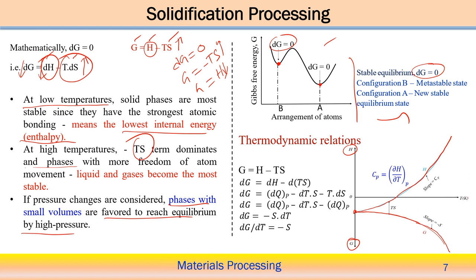If you see, as the temperature is increasing, the Gibbs free energy decreases. That means a more negative value. So Gibbs free energy decreases with increasing temperature. It means that if we make a boundary here, the higher temperature side represents the existence of liquid and gases, which become more stable because the Gibbs free energy is very low. On the low temperature side, the solid phase is more stable, because in this case the Gibbs energy is lower, but not the lowest as in the liquid and gaseous phases.